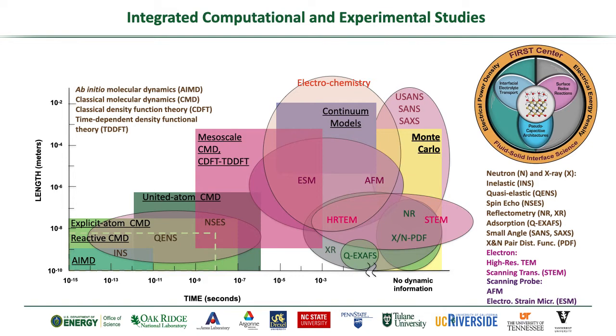Superimposed on this are ellipsoids that show the time and length scales in the available experimental methods used in the center. By design from the very beginning of the center, when we developed a version of this diagram for the original proposal, we have chosen experimental probes that in many cases overlap in both time and space with the computational approaches, or overlap in spatial resolution. This confluence of scales enables two important things: validation of computational approaches by experiment and understanding of experimental results through modeling. Note that neutron scattering methods, inelastic neutron scattering, INS, quasi-elastic neutron scattering, QENS, and neutron spin echo spectroscopy, NSES, probe much of the same spatiotemporal scales as classical molecular dynamics.